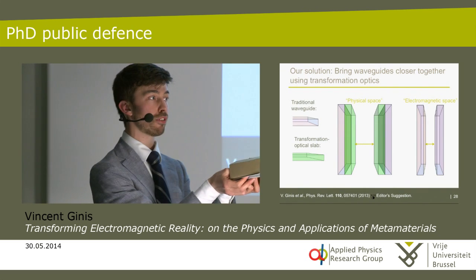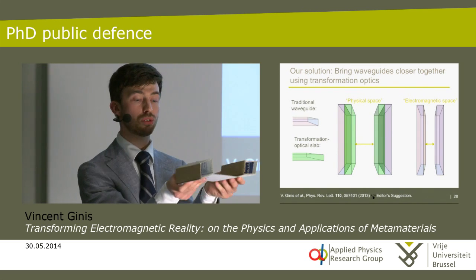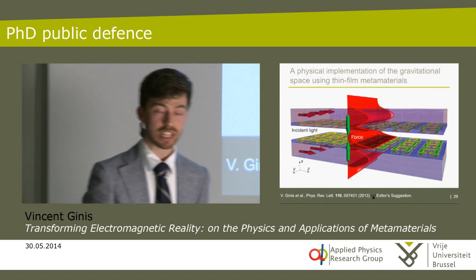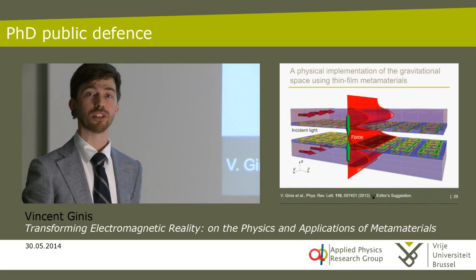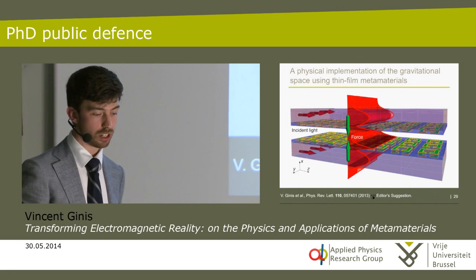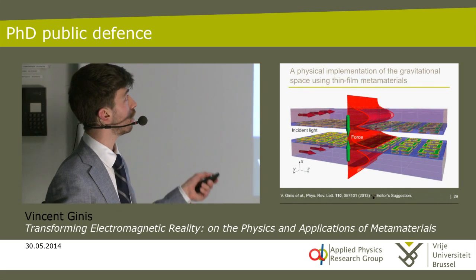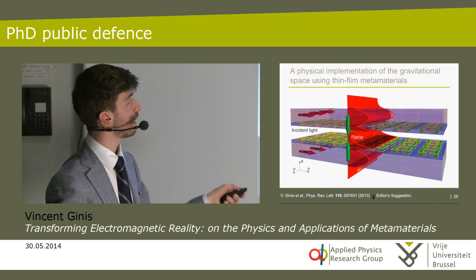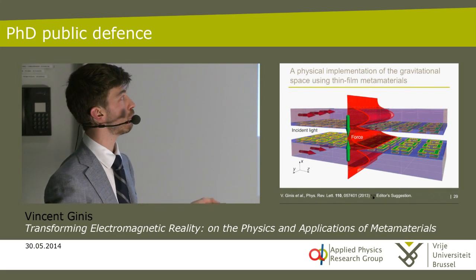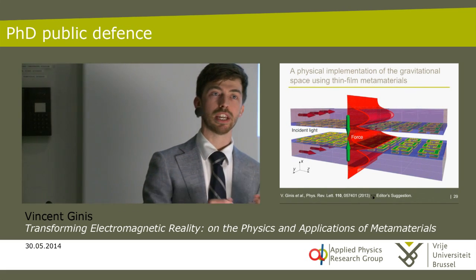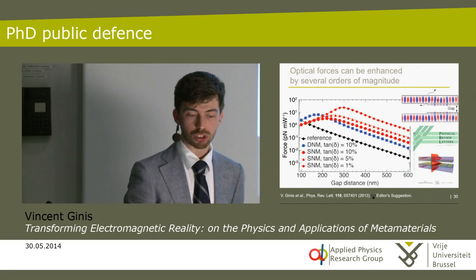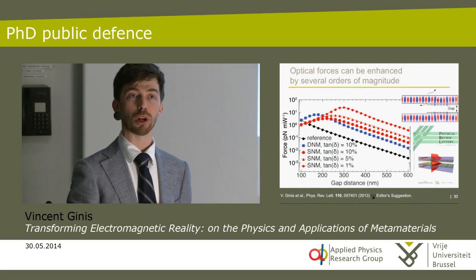So this is a type of coordinate transformation that we wanted to implement. And to implement such a coordinate transformation, we needed here again a specific metamaterial. And this is shown on this slide over here, where we're looking at the 2 traditional waveguides here in the light blue, and then we attach to it a metamaterial cladding, which consists of an array of small metallic inclusions in a silicon background. I think I can best proceed to the final result that we obtained over here.